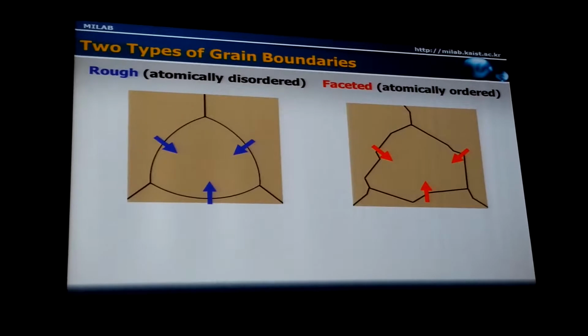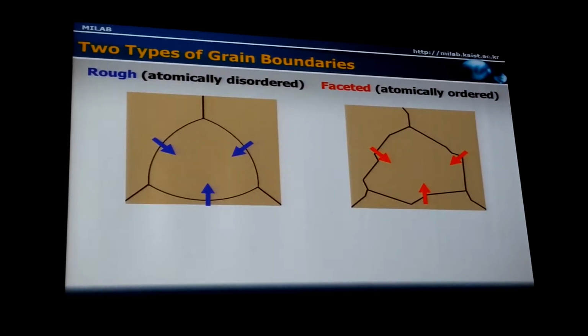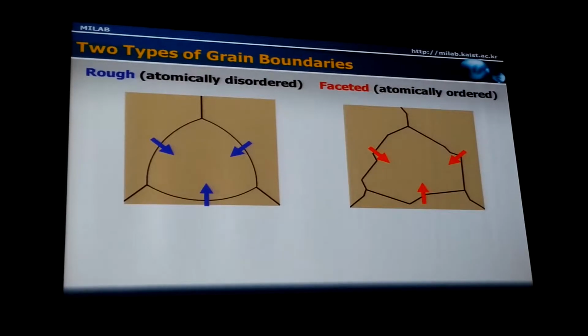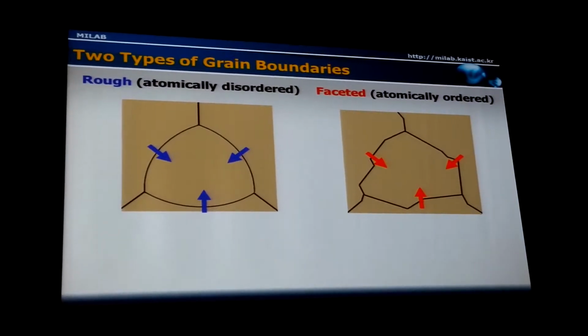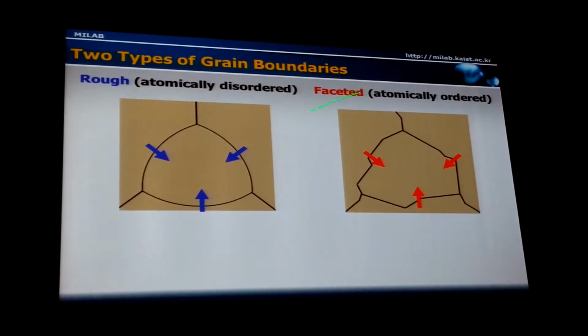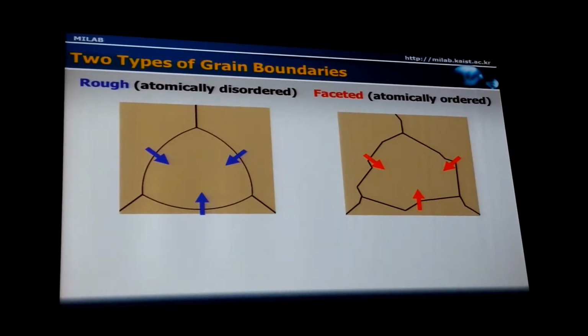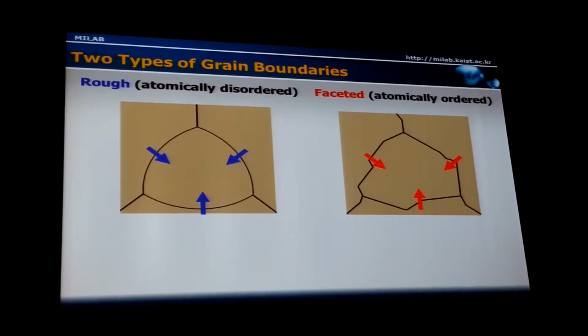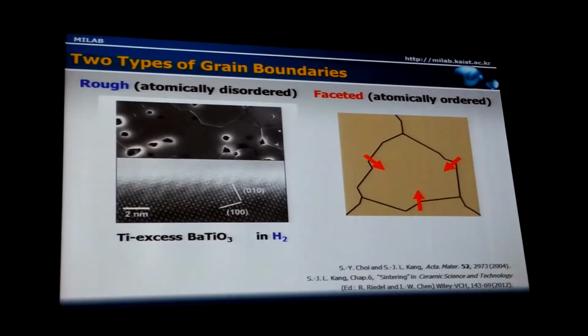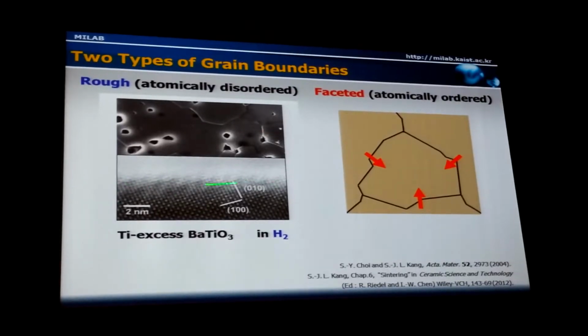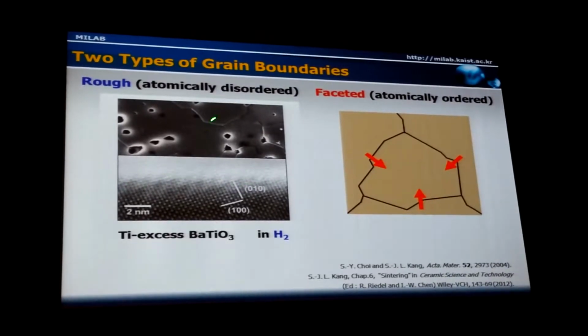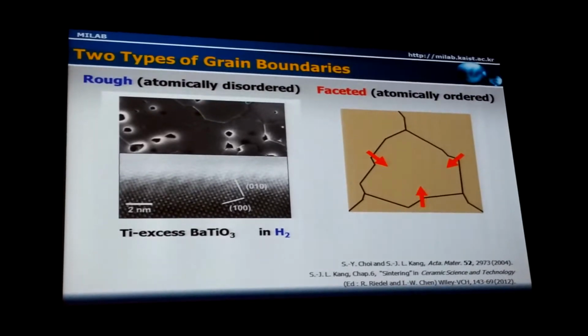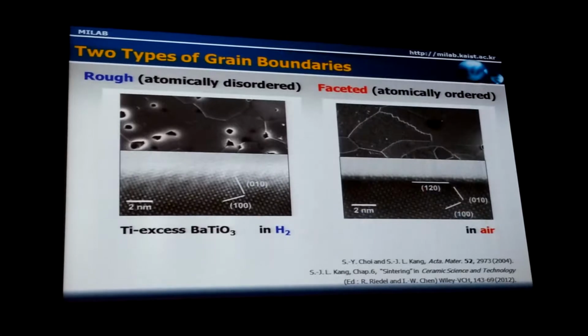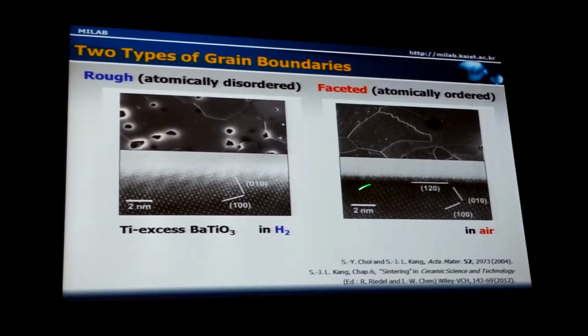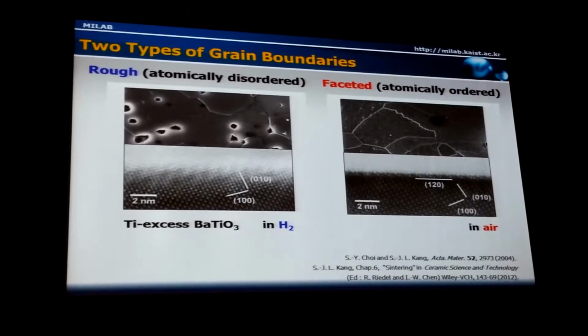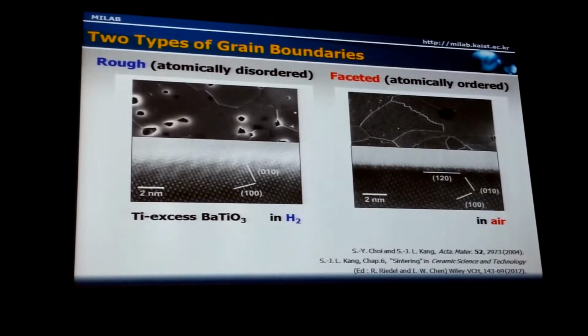Then, how about the case of the grain boundary? The grain boundary can also be categorized into two types: rough, rounded, and faceted. When you look into the grain boundaries under a high resolution electron microscope, the rough boundary has an atomically disordered structure, and under sintering in the presence of liquid phase, the boundary is rounded, curved. But in the case of a faceted boundary, the grain boundary atomic structure is fairly ordered. So there is a difference in atomic structure at the boundary.